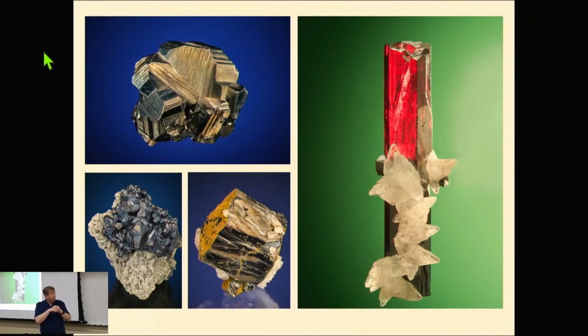Now occasionally, as that one crystal on the far right-hand side shows, you can get spectacular color when you come light through it. The good part about this is these bonds are much more difficult to break than those in proustite. So if you decide you want it under UV all the time, proustite will eventually probably darken. The top picture there is a complexly twinned cluster of proustite from Huancavelica in Peru, and that's a natural color that you're going to see eventually for all these, a silver reflectance. But most of the time you can get some red through that. The one with nice pyrite epitaxial growths on it is from Fresnillo, and the other one is from St. Andreasberg.